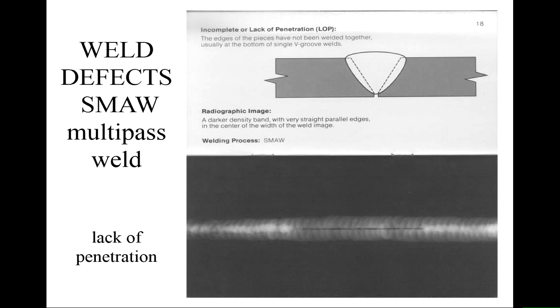So, just as an example here, we've got lack of penetration. So you can see the weld design at the moment. The capping passes and the filling passes have been done well, but the first pass didn't completely melt the root. And if you look at a radiography result, you can see that we've got a nice weld here, and then there's this dark line down the middle, where it's passed through more air, so there's less absorption of X-rays. So that dark line tells you exactly that's where the lack of penetration is. And it's right down the middle of the weld, so pretty much that would be a root pass defect.